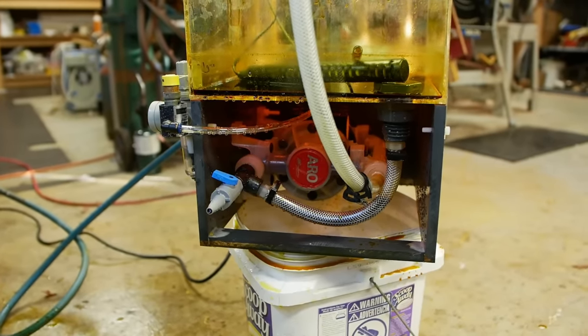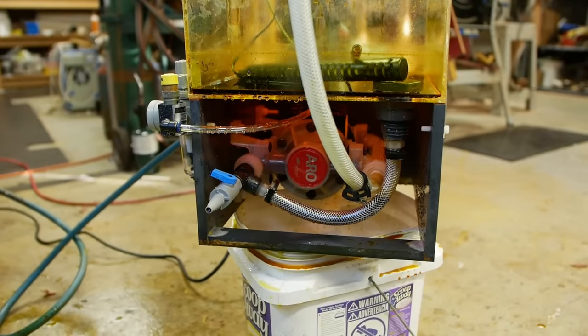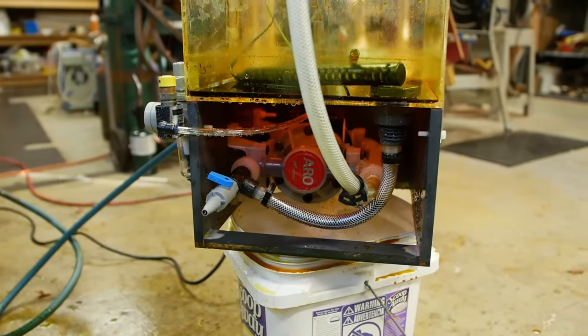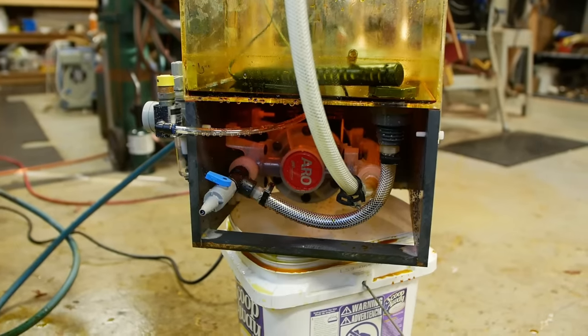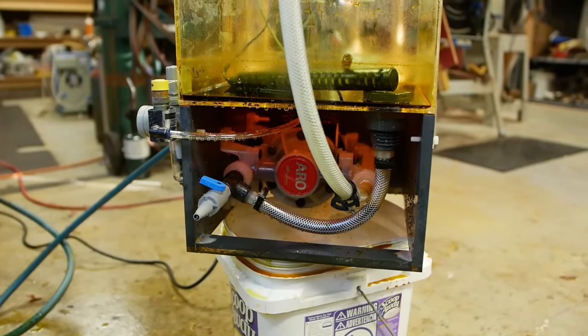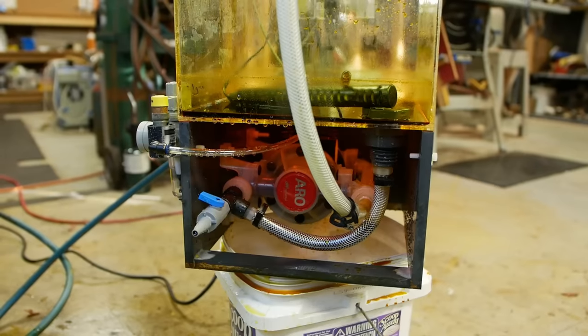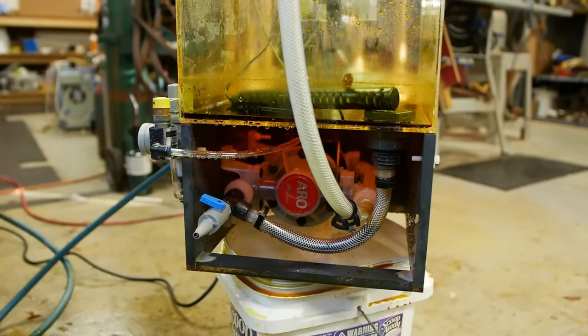The trick is you need a really high pressure and flow rate of etchant to do a good job etching. The difference between just submerging the piece of metal into even a stirred beaker of ferric chloride is nothing. It's about 10 times slower than spray etching like this.